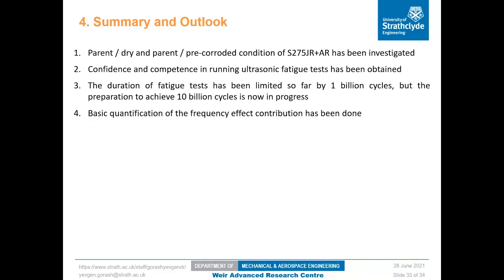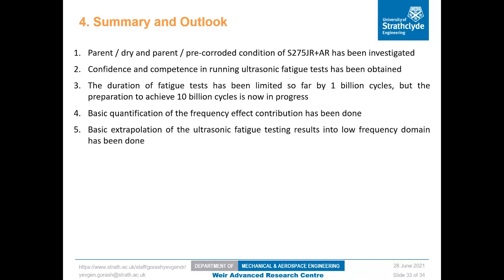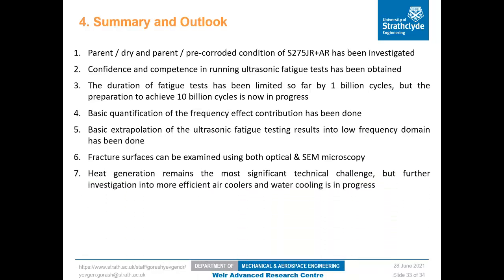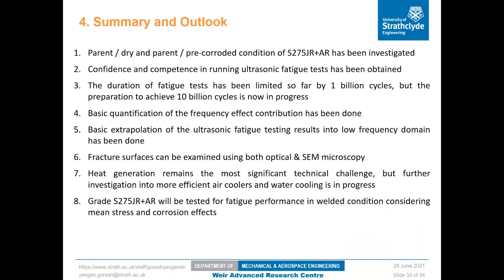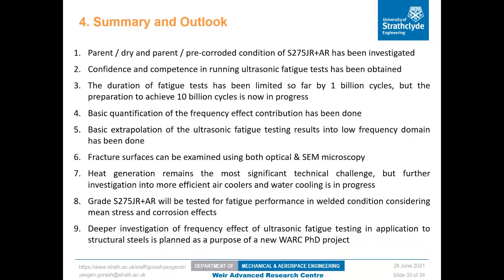Basic quantification of the frequency effect contribution has been done. Basic extrapolation of ultrasonic fatigue testing results into the low frequency domain has also been done. Fracture surfaces can be examined using both optical and scanning electron microscopy. Heat generation remains the most significant technical challenge, but further investigation into more efficient air coolers and water cooling is in progress. Grade S275 will be tested for fatigue performance in welded condition considering mean stress effect and corrosion effects. And deep investigation of frequency effect and ultrasonic fatigue testing application to structural steels is planned as the purpose of a new PhD project starting next year.